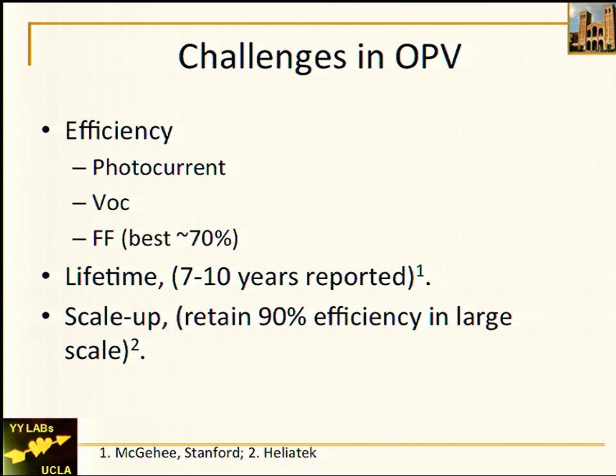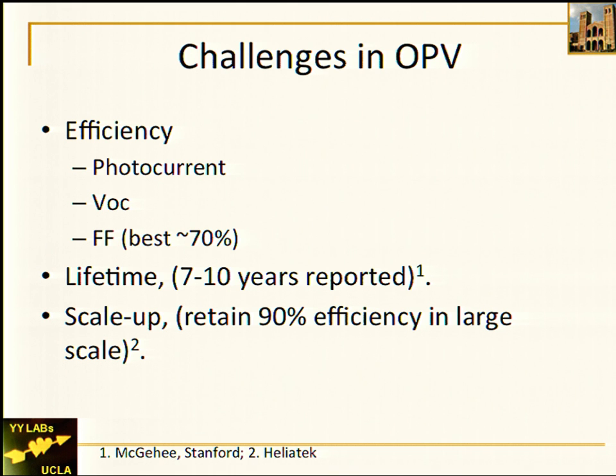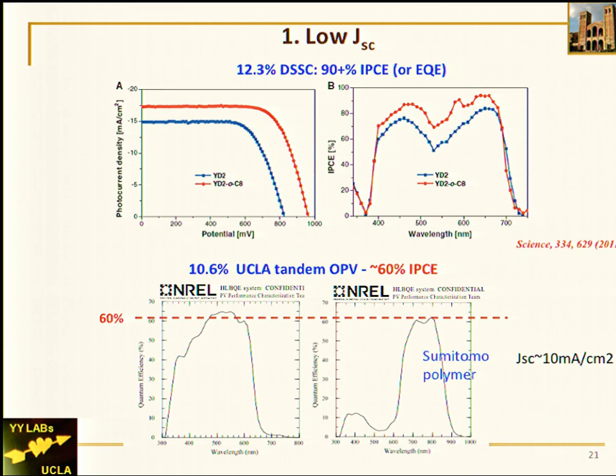Now I'd like to address the challenges of organic photovoltaics. When Zakya asked me to talk about the future as well, I said sure. We know photovoltaic performance can be divided into photocurrent, Voc, fill factor, lifetime, and scale-up. DuPont Display discussed scale-up, so I will skip that, but the important issue is how much efficiency drops when scale-up occurs. Heliatek can retain 90% of efficiency when transferring to larger scales; we can probably retain only about 70%. For lifetime, work at Stanford on P3HT:PCBM solar cells shows seven to ten years, which is very encouraging.